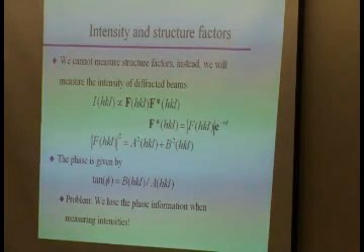Now, there's nothing complex left, is there? That has certain advantages: we can actually do math with it, no i's. So we like that. It also means that we lose the phase information. We get the magnitude, but we don't really have the phase anymore.